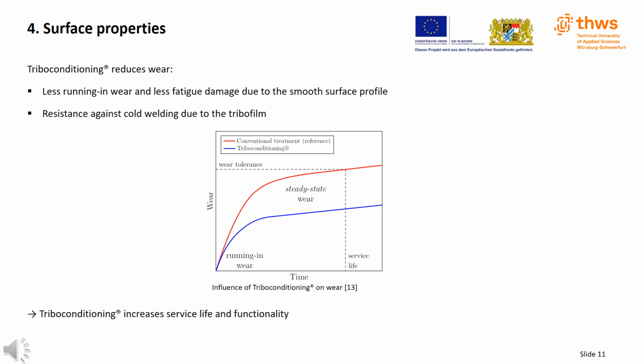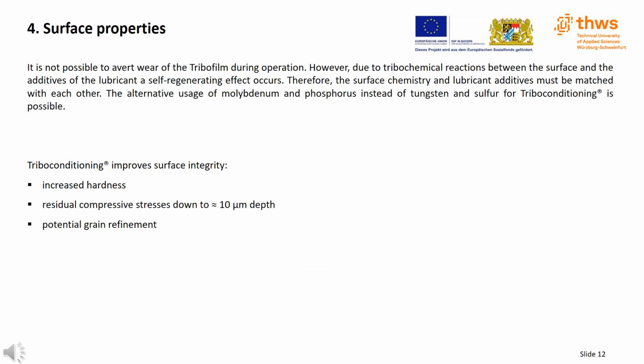As just described, the running-in wear of triboconditioned parts is lower. As a result, the amount of wear at the beginning of the so-called steady-state wear is lower than that of the reference part. At a given tolerance level, this leads to a longer service life and increased functionality due to triboconditioning. During operation, wear of the tribofilm cannot be avoided. However, there is a self-regenerating effect due to tribochemical reactions between the surface and the lubricant, or rather its additives. Therefore, the reactants of triboconditioning must be matched to the lubricant in the subsequent application. Thus, unfavorable triboreactions associated with adverse changes in the properties of the surface can be avoided.